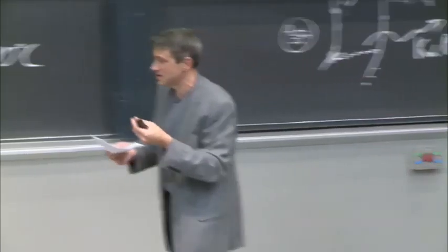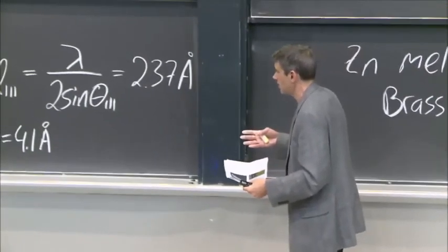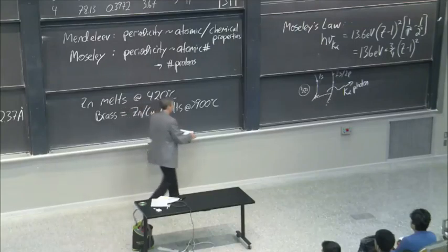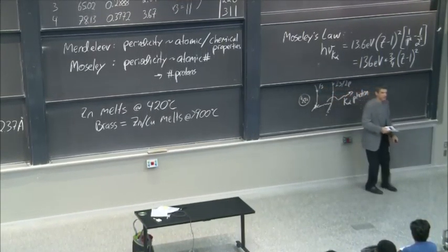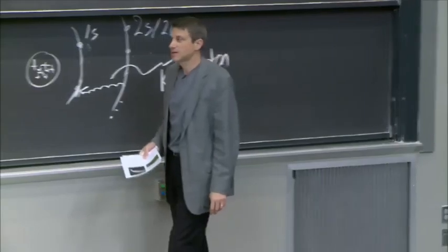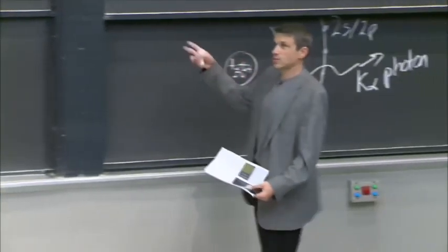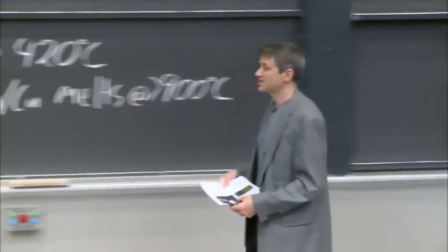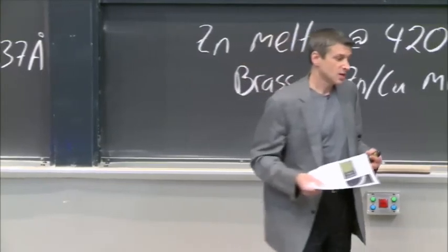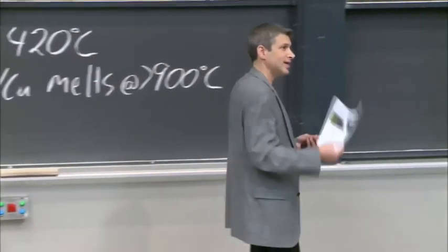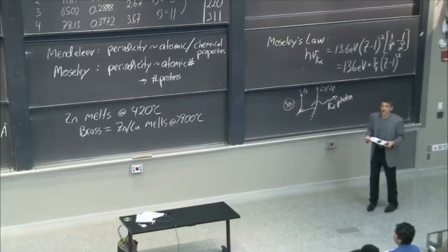Now some of the time you get the transition that we talked about. You knock an electron out and you emit a photon, a K alpha photon, or maybe an L beta photon, right? And sometimes you slow the electron down so you get the Bremsstrahlung. Yeah, but there's so much energy being pumped into this material. And a lot of times, those electrons just collide and heat up the metal. That metal is getting extremely hot.